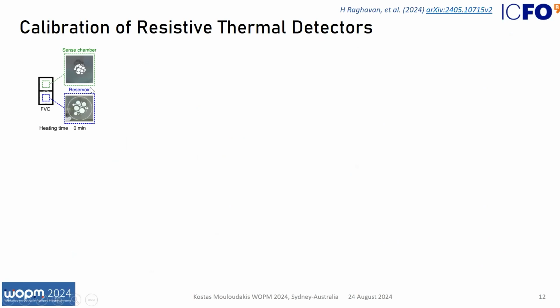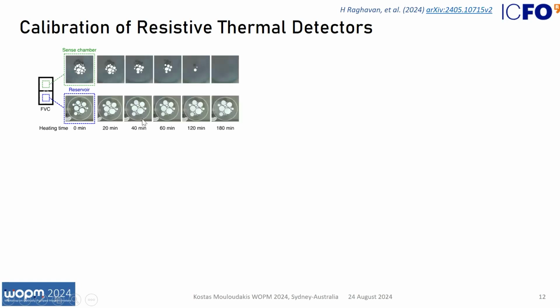After the cells are fabricated, they look like this. There is a lot of condensed rubidium on the glass, both of the sense chamber and the reservoir chamber. Actually, this rubidium azide decomposition process produces a lot of rubidium. And we use a heating process where we continuously heat the vapor cell with 1 watt of power at 100 kilohertz AC. After 3 hours, we see that the condensation from the sense chamber has all moved to the reservoir chamber. And at this point, we have a temperature gradient between the two chambers of about 40 degrees Celsius.